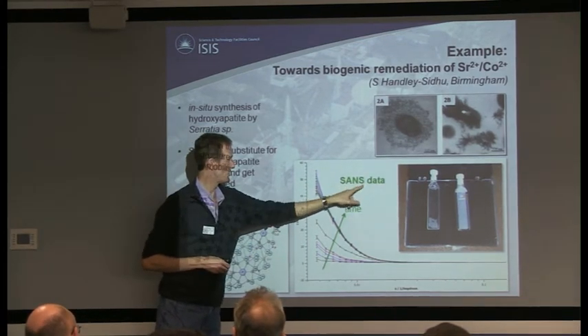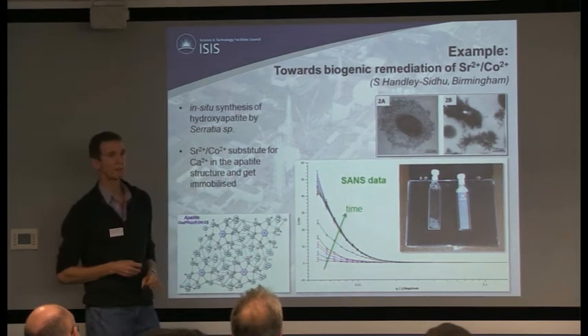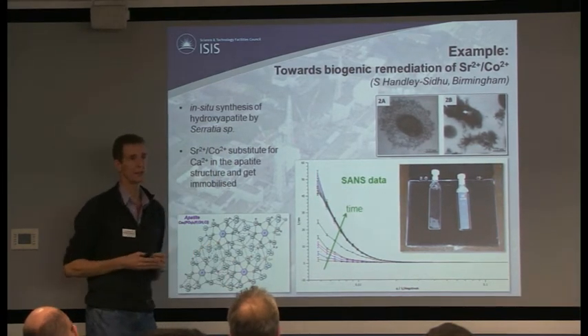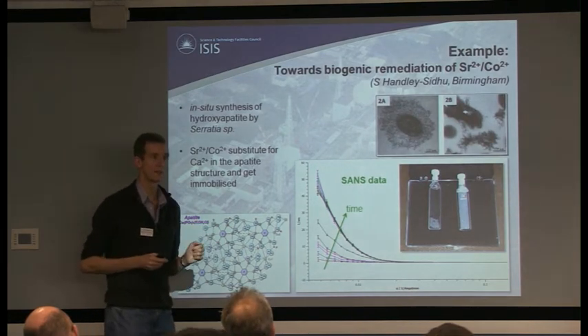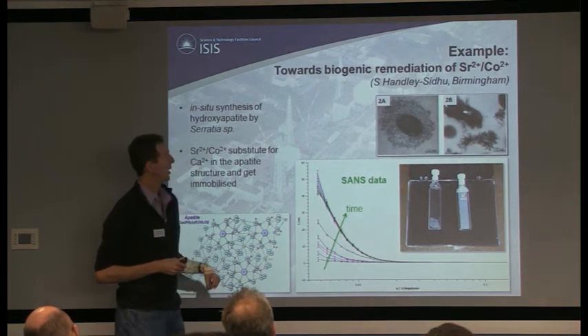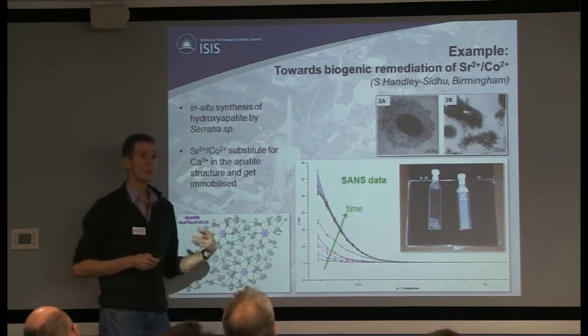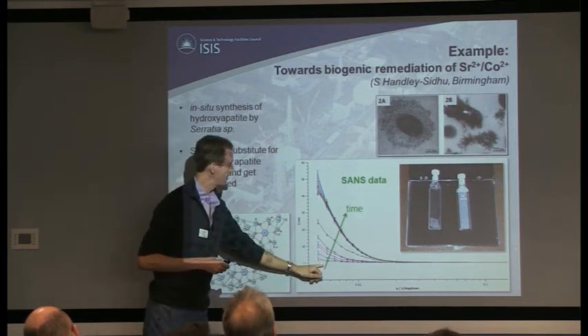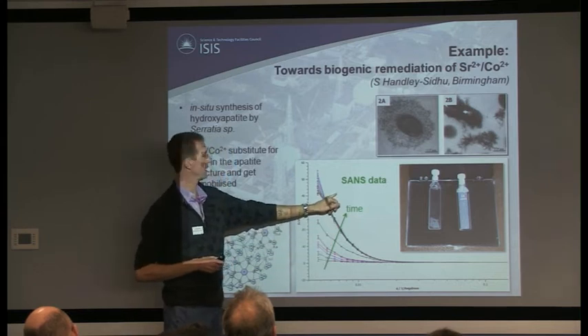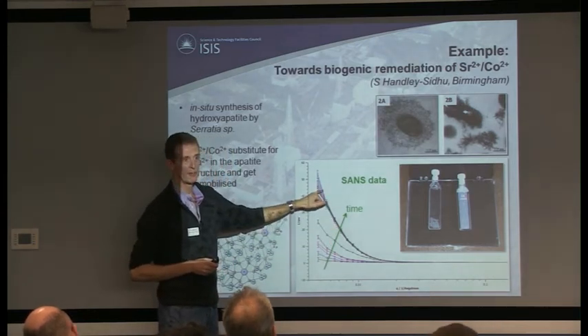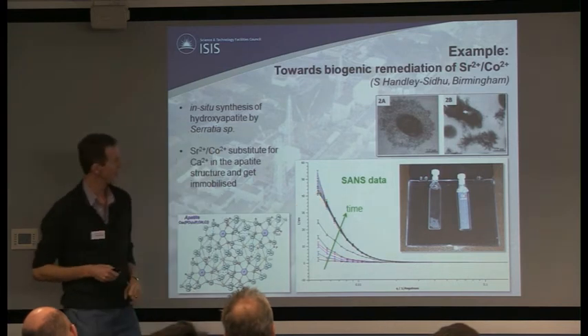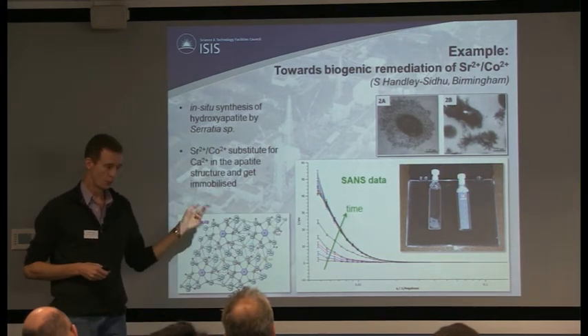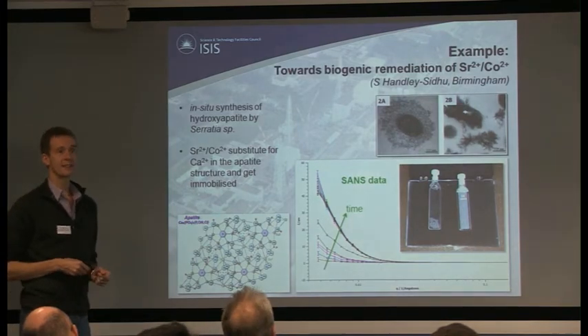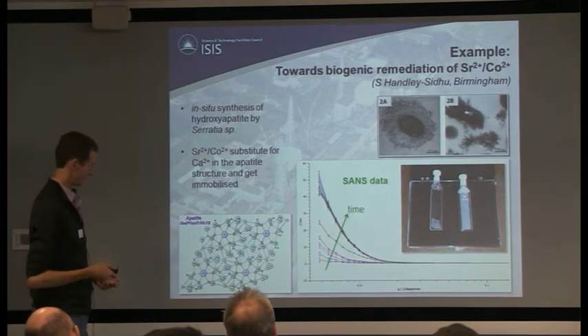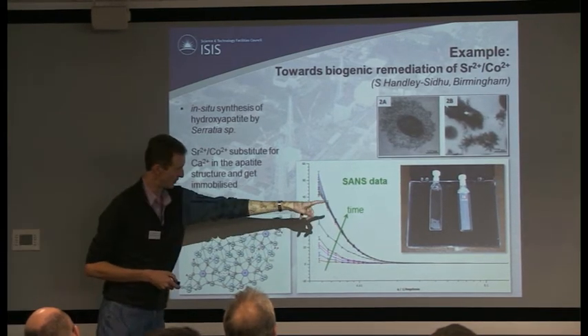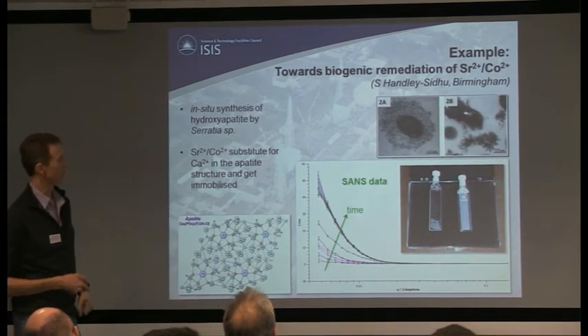This is a neutron technique called small angle neutron scattering. So it's looking at relatively large length scales, sort of the 1 to 100 nanometer length scale. Okay, and then we fed it something that would allow the formation of the hydroxyapatite, and with time you can see that we actually see an increase in the scattering here, and it obviously reaches some form of limiting level, and from that we should be able to get some idea of what the kinetics actually was. The example there, you can actually see it does form crystals.